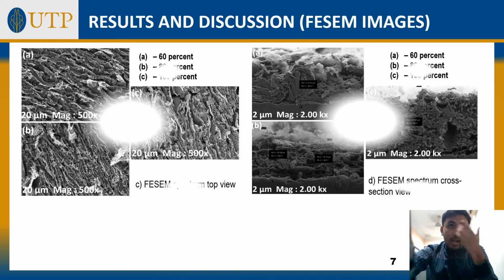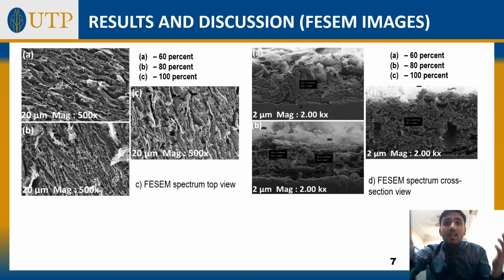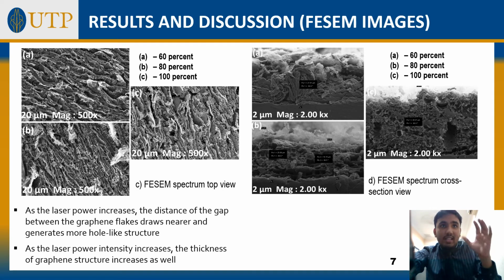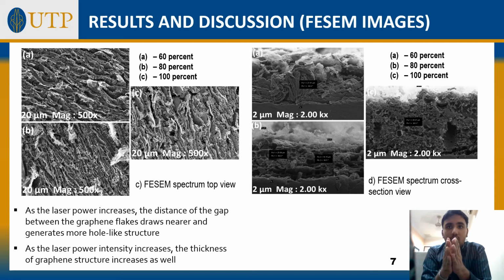Next up, sir, I would like to talk about my field emission scanning electron microscopic results in discussion. On my left side is the top view of the laser scribed graphene, with an equal scale magnification of 20 micrometer and also 500 times magnification. The observation that we interpreted is that as the laser power increases, the gap between the graphene becomes smaller, and it also produces hole-like structures between the graphene flakes due to increasing graphitization level from increasing laser intensity.